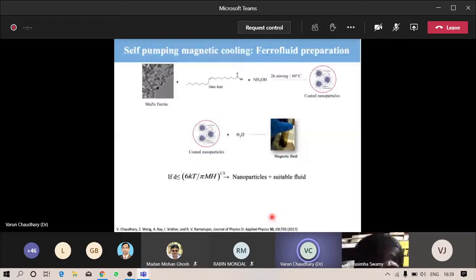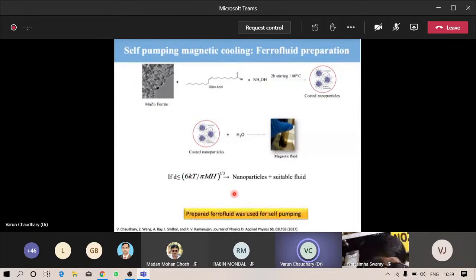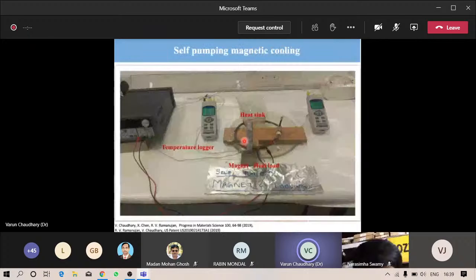As the medium to carry and remove the waste heat, we use the ferrofluid. A ferrofluid is nothing but a dispersion of magnetic nanoparticles in a medium, and that medium can be either water or oil. The condition is that the particle size should be in the nanometer range. So we have prepared this ferrofluid for MnZn ferrite base, and later we also worked on only ferrite-based ferrofluid in oil.